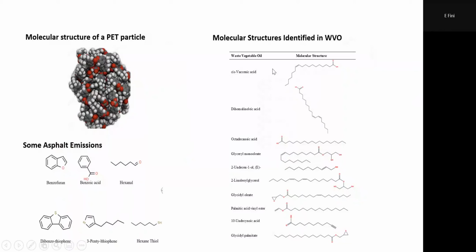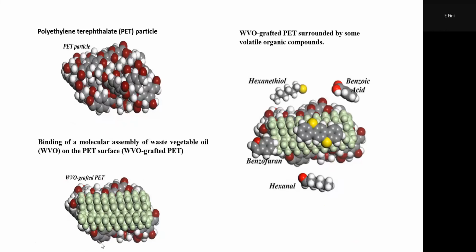But if you think about all the molecules of the oil, which we put on the face of the plastic, these are the molecules. So we basically put these molecules on the face of the plastic. And this one here on the left is the plastic. So when you get the plastic, cover its face with this oil, and then mix it with asphalt here, you will get something like this, grafted. So the oils are grafted to the plastic and become like this, the one on the right. And when it becomes so grafted, when the oxygen comes to attack the material, it will be delayed. So some of this aging will be delayed because of the interaction.